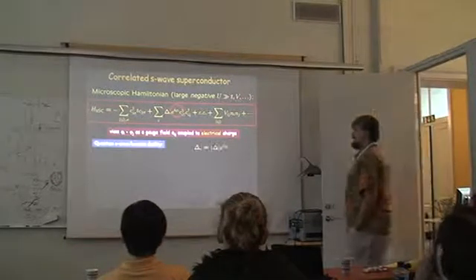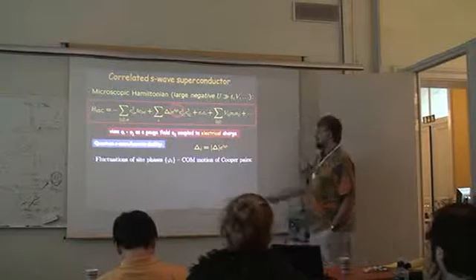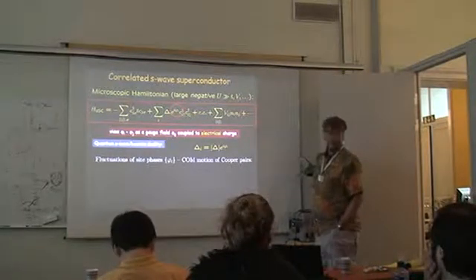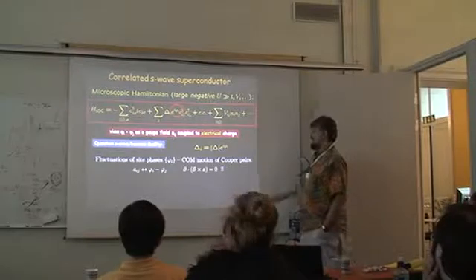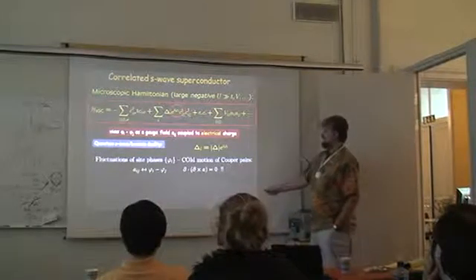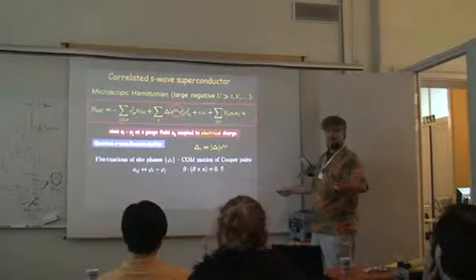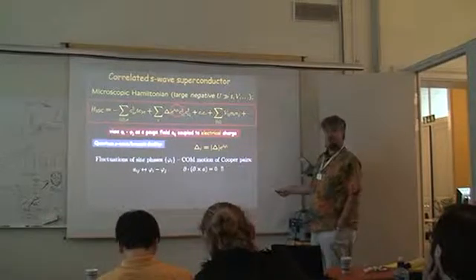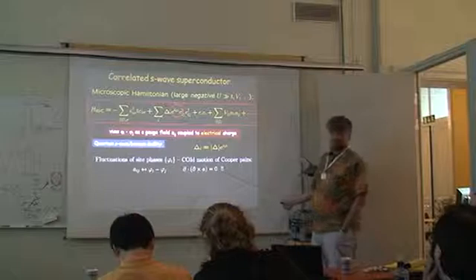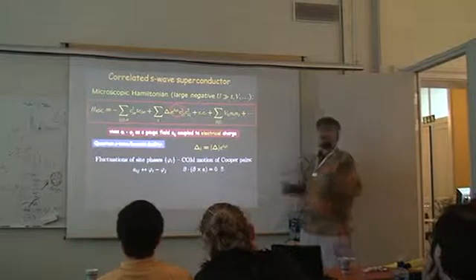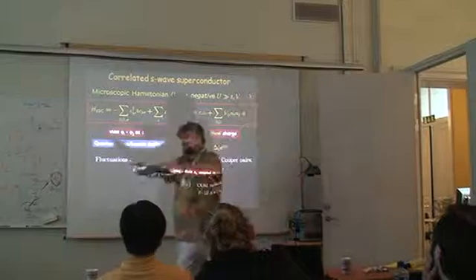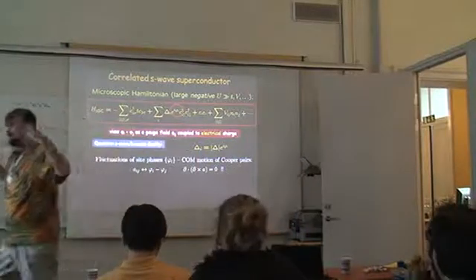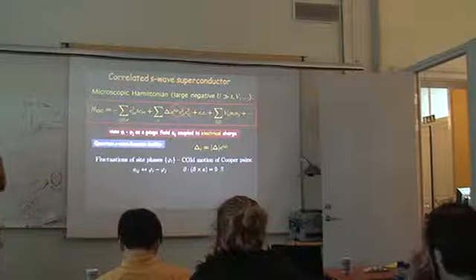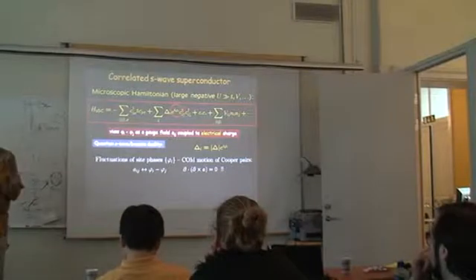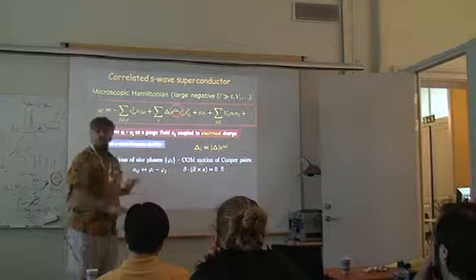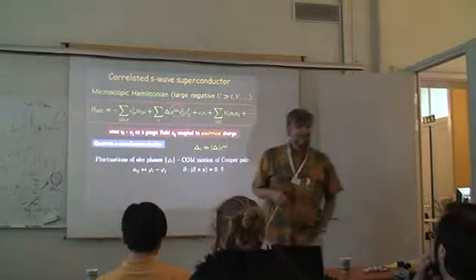And then we can use this duality, as I mentioned, where the fluctuations of this phase correspond to center-of-mass motion of Cooper pairs. And here is our famous gauge field. We take the 2 plus 1 dimensional divergence. The plus 1 is the time direction of this gauge field on a lattice, and it's equal to 0. This is very good because it tells us that whatever configurations these phases take in 2 plus 1 dimensional space-time, they can be described as configurations of vortex and anti-vortex packets. This is basically a conservation law for vortices. Does that make sense? A little bit.